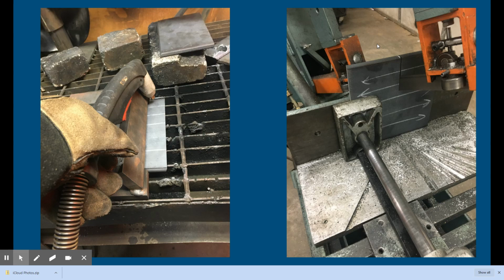So you could have a perfect weld, but because the crystalline structure of the metal is set up lengthwise going across your bend, it's going to be more likely to break instead of bend. So very important. You could fail a bend test just by cutting the metal the wrong way. If you're doing this in industry, you're probably ordering coupons from a company, and they're probably stamped with a heat signature, what grade of metal they are. There's probably a serial number that goes along with it.